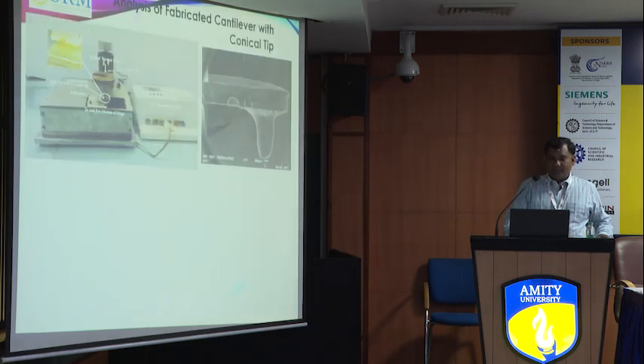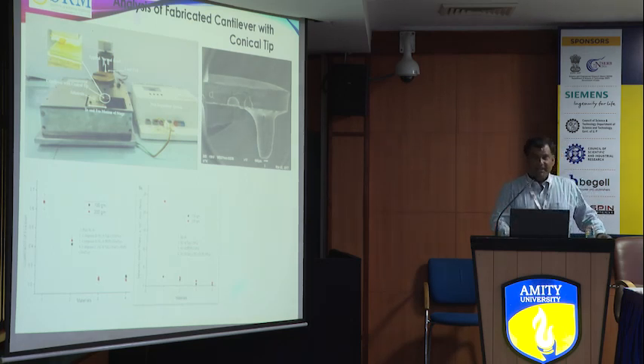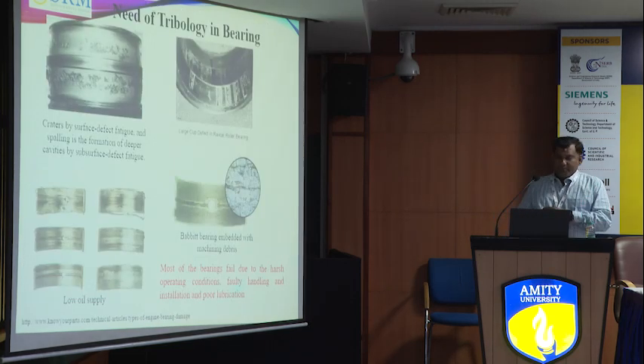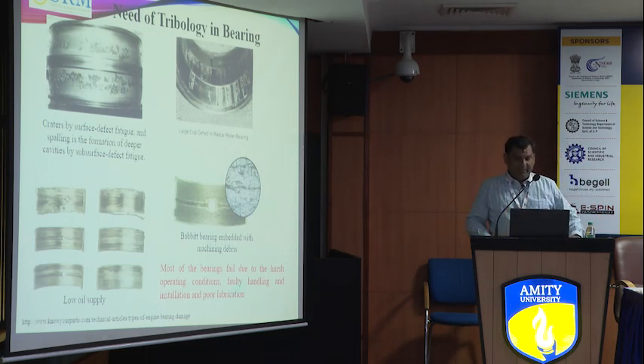And this was the beauty of this work. Then after that I also fabricated the composite tip. That is a micromechanical tip, a few microns to 500 microns, and we obtained a similar type of result, so that we concluded that particular thesis. Similar results showed that fluorine is transferred, due to which your friction is less and the life of the tip is also improved. So now we move to the next part, bearings.